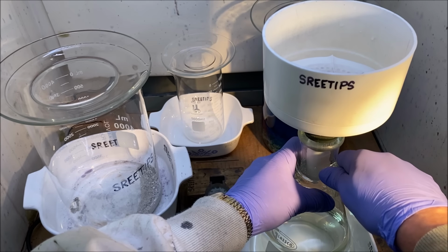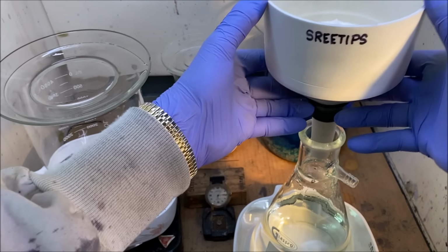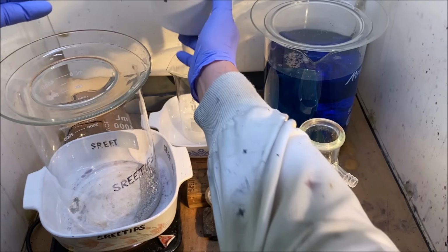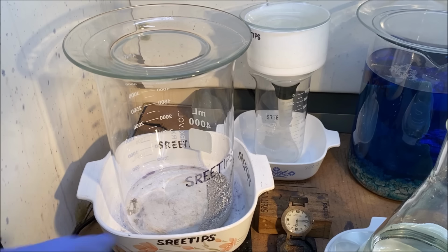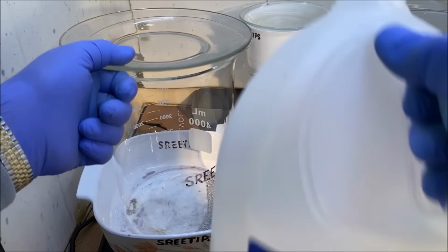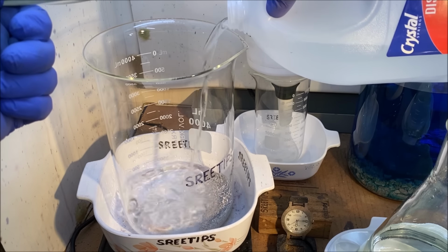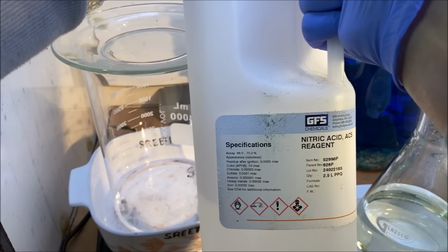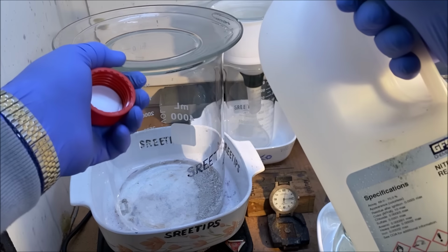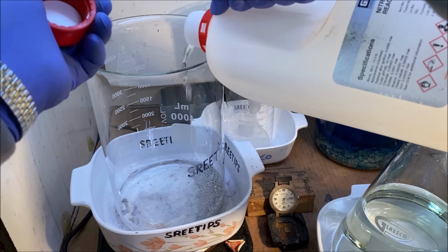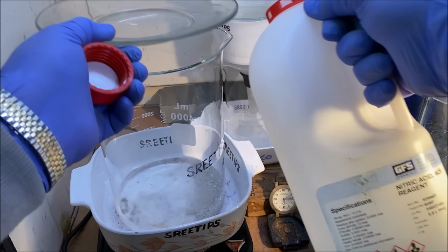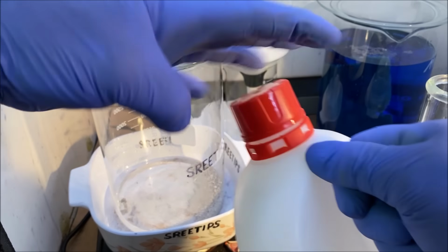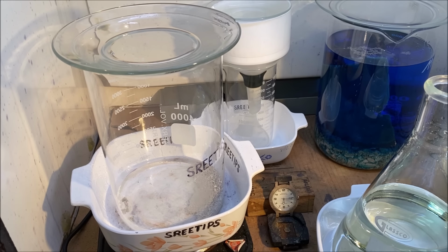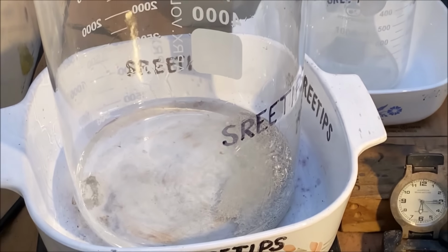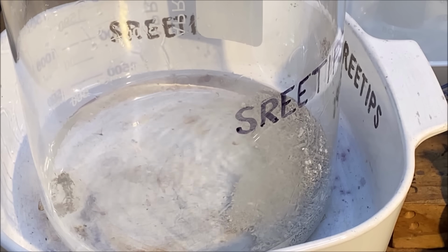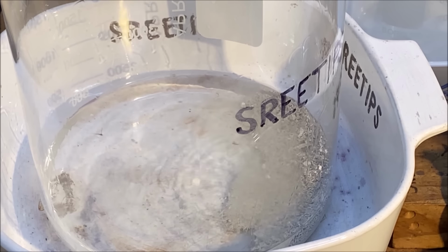All right, we got the solution filtered. Take this funnel off of here, stick it back here out of the way. There's probably 100 grams of pure silver left down in the bottom of this beaker. I'm going to add a little bit of distilled water and a little bit of nitric acid to dissolve a little bit more of this silver that's in here. We'll use this as spare electrolyte to replenish the electrolyte in the silver cell as it runs, because the electrolyte does become depleted as the cell runs, and due to evaporation, the electrolyte level will drop as the cell runs.